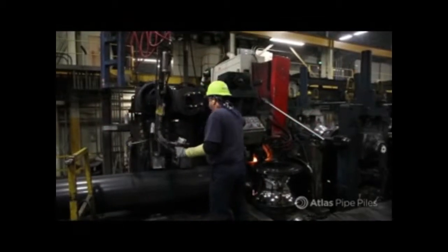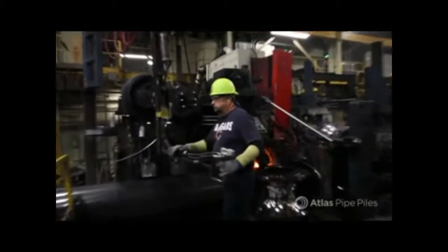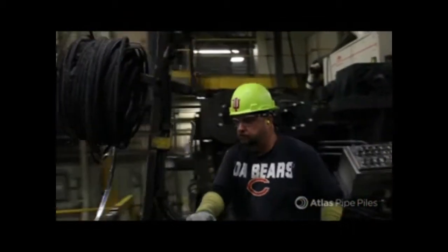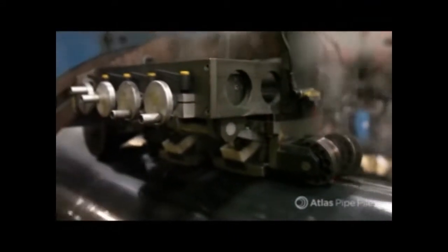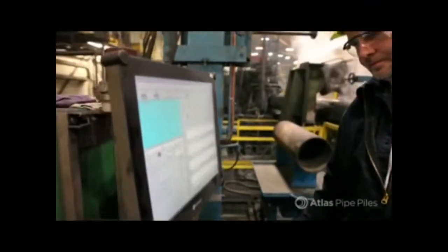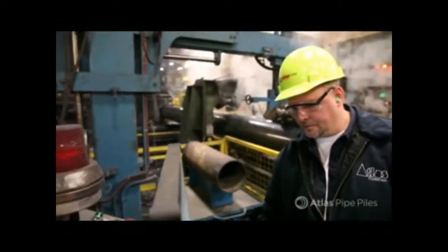Any excess seam from the weld is carved off by the scarf cutter, making a smooth and almost invisible seal. And then the pipe is ironed while the weld and pipe is still hot to get the right size and diameter for installation. After the ERW welded seam is complete, the pile moves on to ultrasonic testing. This test checks the integrity of the electric resistance weld and detects the presence of any internal flaws. Any defects are automatically cut out and part of the Atlas 100% quality guarantee.